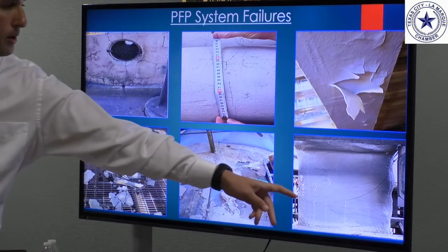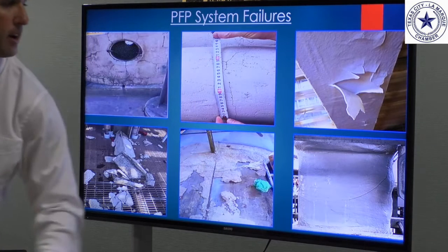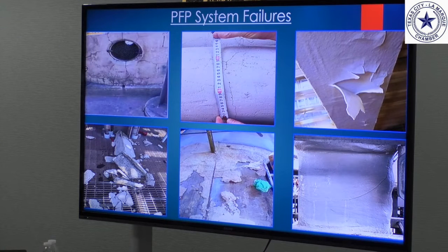The photo below, you can see a stress crack right here. This scenario, it's an equipment pedestal. Now the applicator did not control the film thickness as they were applying it, and they applied it well above and beyond any tolerances that are recommended by the manufacturer. What this does is create an extreme stress on the coating, which leads to the cracking that you see. Again, it's the same type of failure mechanisms. You're going to start getting moisture behind this coating system, and eventually it will lead to a failure.